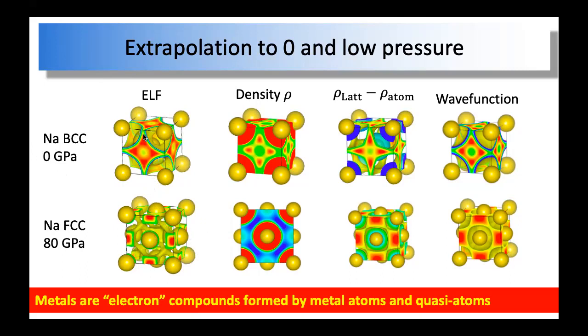So you can see that ELF has a maximum localized at the deformed tetrahedral center of a BCC structure. Right, so here's a tetrahedron. You have 2 sodium here, 1 sodium here, and 1 sodium up in the front. Right, so you have 4 sodiums. So here, this is the center of that tetrahedron. It's deformed, it's not perfect. And the maximum is right at here.